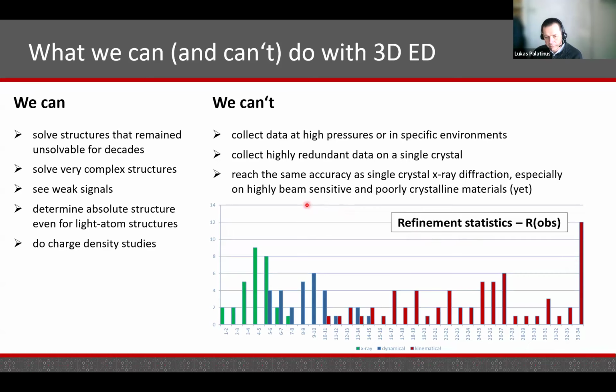This is another histogram of R factors. Red is a collection of R factors from a broad number of materials, from organic to inorganic. You see that the spread is rather large. When we switch to dynamical refinement, things improve considerably, and most refinements approach the level of 10% or below.